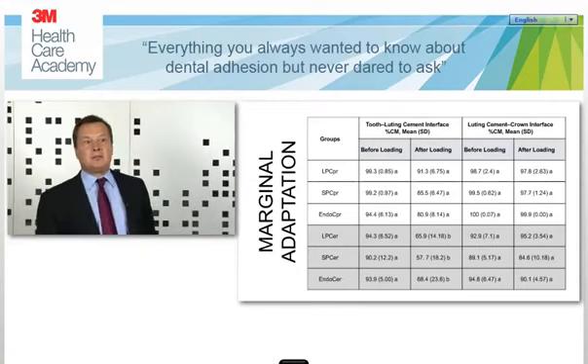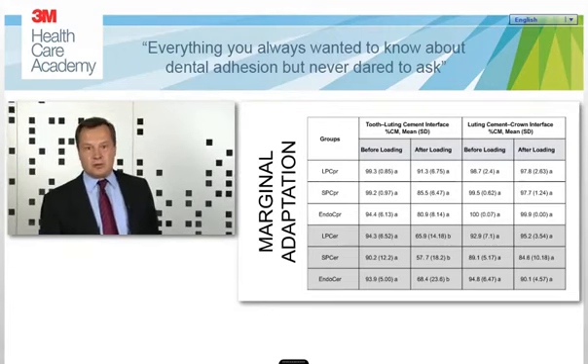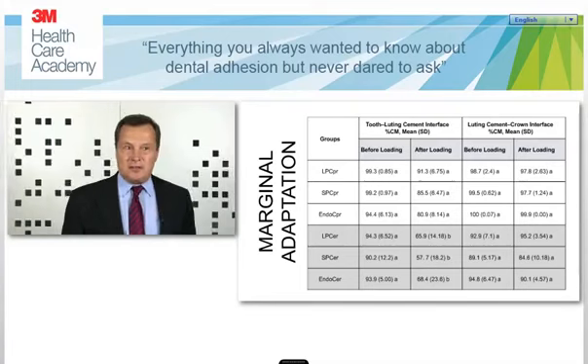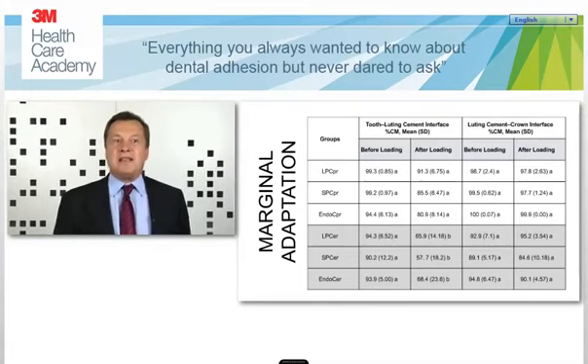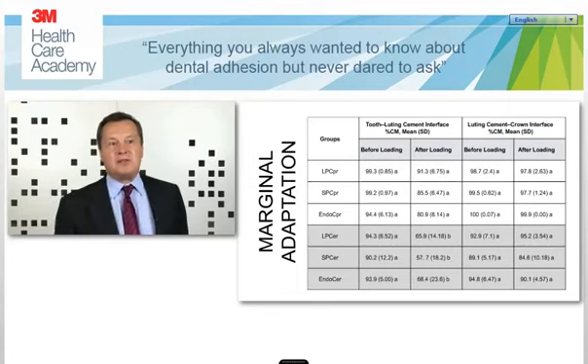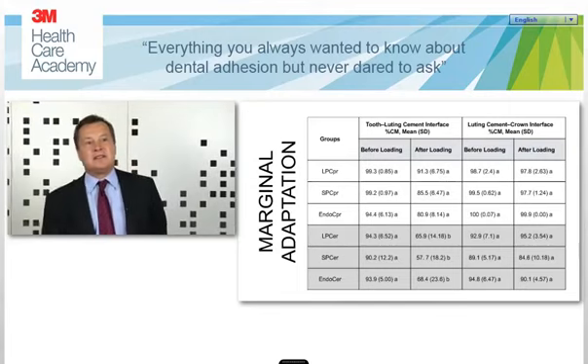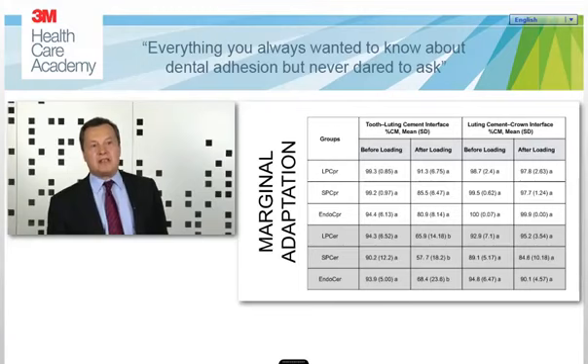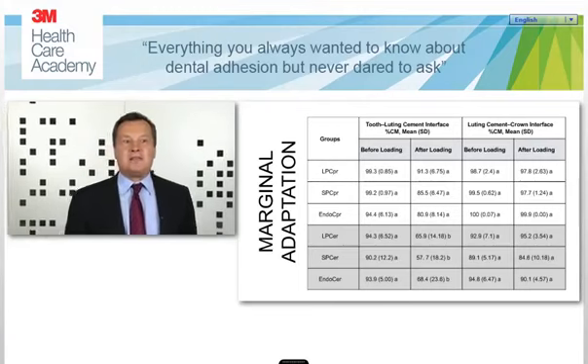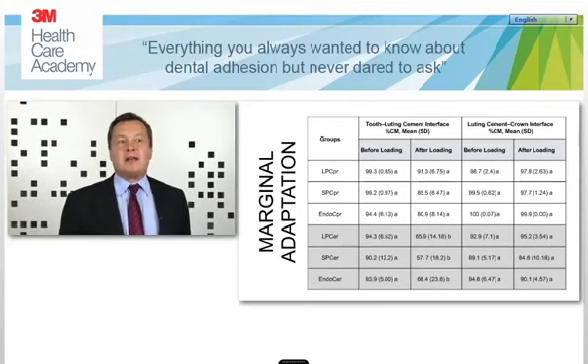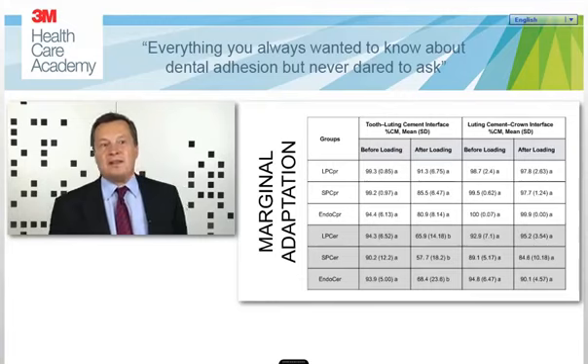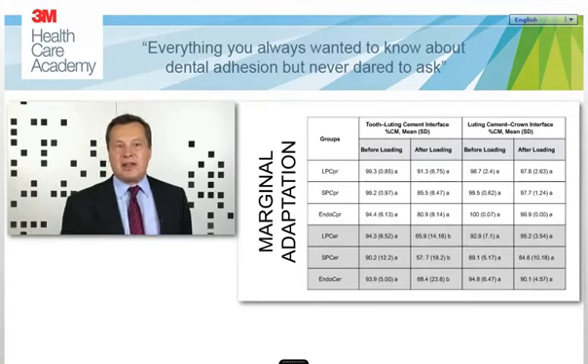Even if the groups with the long post and the short post were macromechanically retained, and the endocrown was purely adhesively retained. And by comparing composite crowns and ceramic crowns, this is the difference between the white groups and the gray groups. You can see that after loading, the composite crowns and endocrowns performed better than the ceramic crowns and ceramic endocrowns.